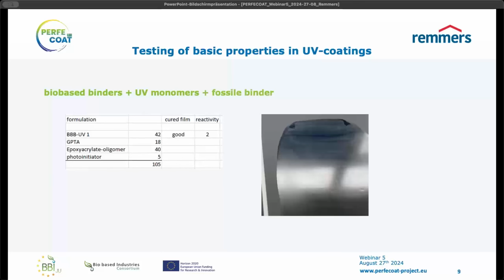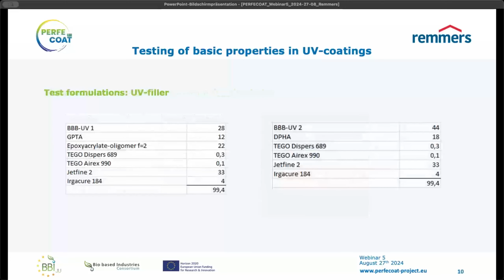We tried to improve that one even more by adding some fossil-based standard binder. So we combined this 70-30 mixture of the binder number 1 and the GPTA with some epoxy acrylate oligomer, and then we had immediately a good film and a reactivity which is also okay. With 2 passes under the lamp, it was fully cured. So from that point on, we had a good base to go for real formulations, and this is how they are looking.